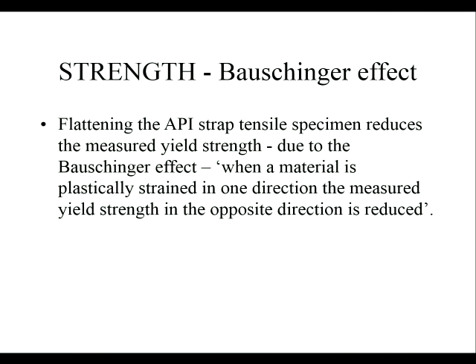Because if you imagine bending something some way, you've actually put some plastic deformation in, you've created what are called dislocations, which are responsible for plastic deformation. When you bend it back the other way, the dislocations that you've already created can move in the opposite direction. They've already been created, you don't have to create them, they just have to be moved. And its usual result is that the yield strength drops when you measure it in the opposite direction. So if you bend it one way and then bend it back, you will have effectively reduced the yield strength. And this is called the Bauschinger effect.